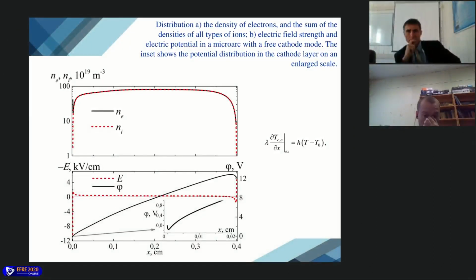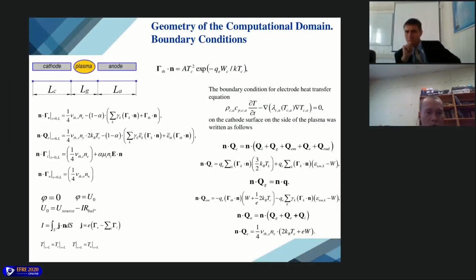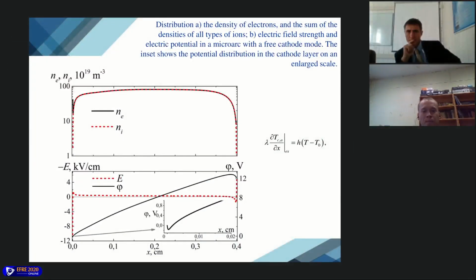Also, it's interesting to investigate how boundary conditions on the opposite side of the electrodes influence the results. The first results we found are for when the temperature is constant, room temperature. And in the second case, we used these boundary conditions. And for the arc region of the discharge, we can see that in the cathode region,